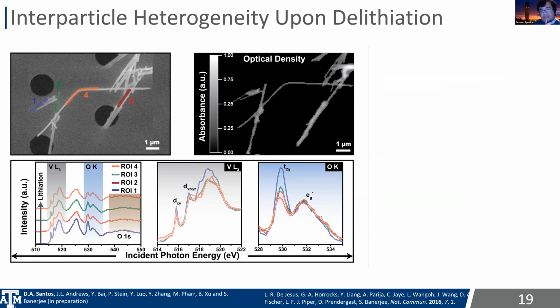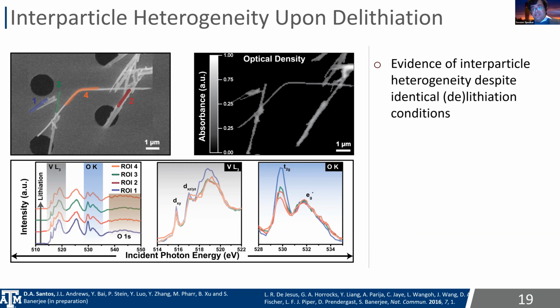This turns out to be quite an important thing because many continuum models of battery systems essentially talk about average forms of lithiation, whereas these images illustrate the great spatiotemporal heterogeneity that exists in these systems as lithiation occurs, and as a result of these diffusion limitations arising from small polaron formation and the resulting phase heterogeneities in these systems.